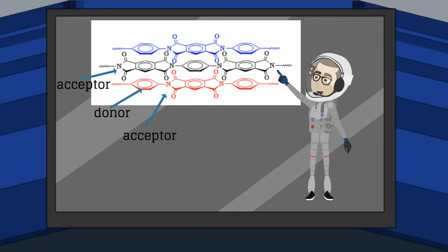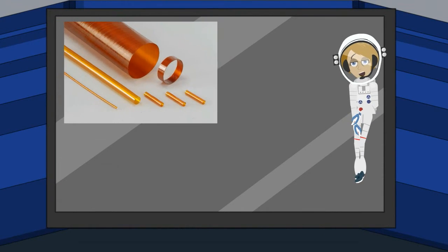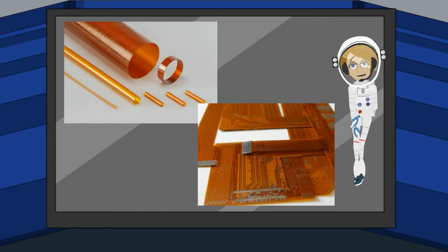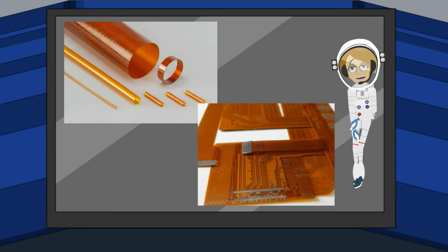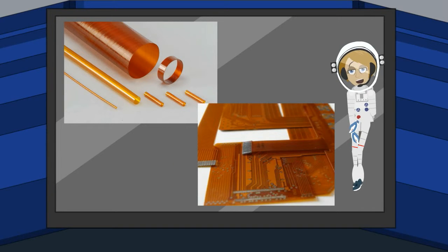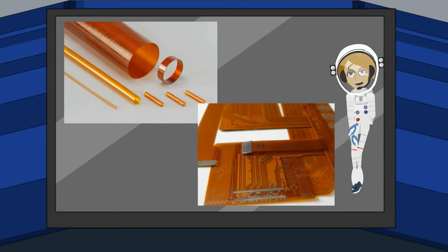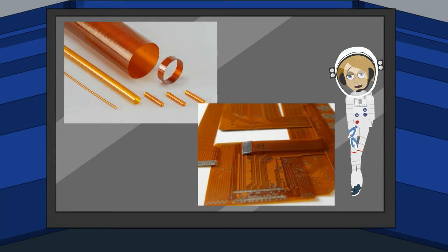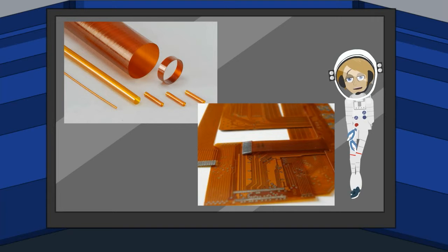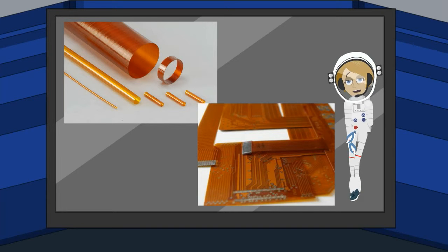These chains stack on top of each other to form layers, and donors and acceptors bond in this direction too. This leads to strong, stiff bonds in all directions. This structure is very important in influencing the properties of Kapton. Kapton is a good insulator. It has a long lifespan and a tensile strength of 231 MPa at 23 degrees Celsius. It also has a low density of 1.42 grams per milliliter. Because of the charge transfer in and between polymer chains, everything is held together tightly from a molecular level.